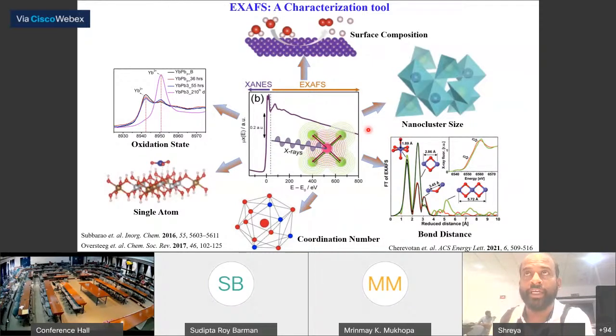and then how the bonding is, and how the bond distances vary. Bond distances introduce various concepts like lattice strain and frustration in the system that can induce enhanced activity. All these fundamental concepts of chemistry we have well used, and EXAFS is used as a complementary technique. Sometimes it is used as an in situ technique, understanding the mechanism in depth.